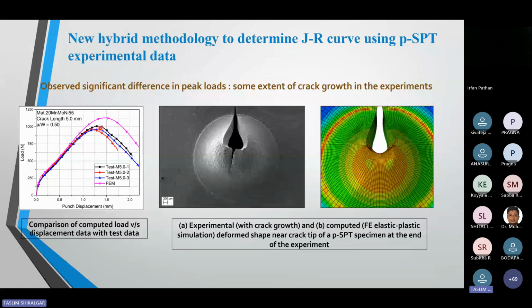I stopped the test at the maximum peak load and I observed this. I observed that my crack is growing at the peak load. So that's why my peak load is not matching with the numerical results. So I observed a significant difference between numerical peak load as well as experimental peak load. And the major reason is some extent of crack growth observed in the experiments. So here I similarly got this image at the peak loads. Here you can see the comparison between the two images. So anyone can understand this difference is because of this crack growth.